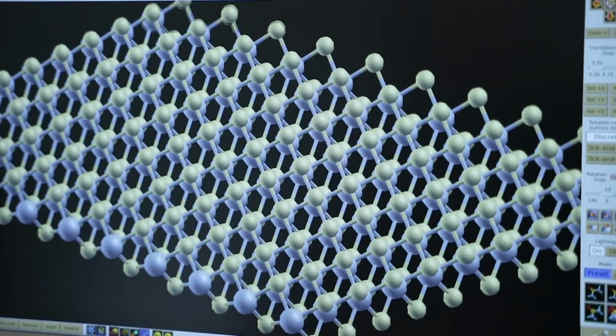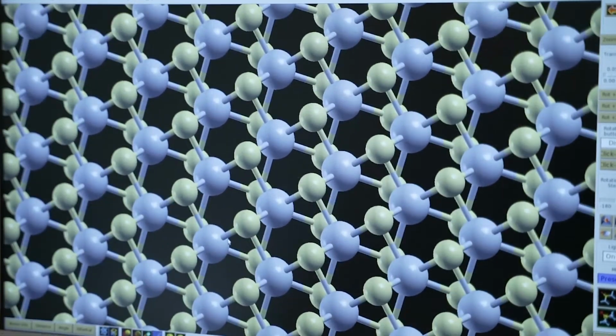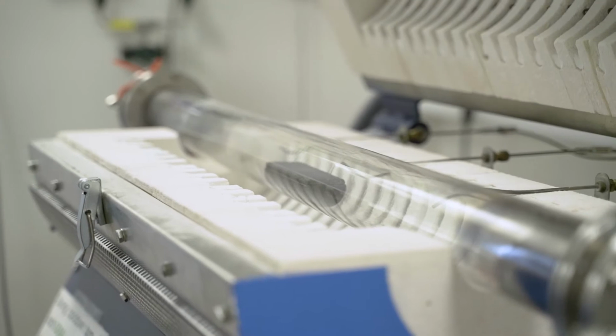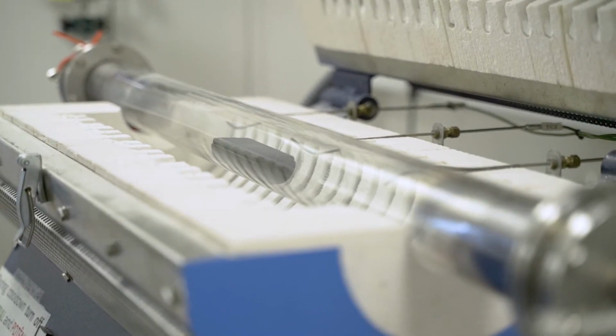In the end, our goal is to fabricate an all-2D-materials photodetector, and for that we need graphene in the first place for the contacts to the active layer, which is a transition metal dichalcogenide. The graphene we can grow by chemical vapor deposition over large areas with a very high crystalline size, up to several millimeters in diameter. And this graphene has the perfect properties to work as an ohmic contact to the active layer made by a two-dimensional semiconductor.